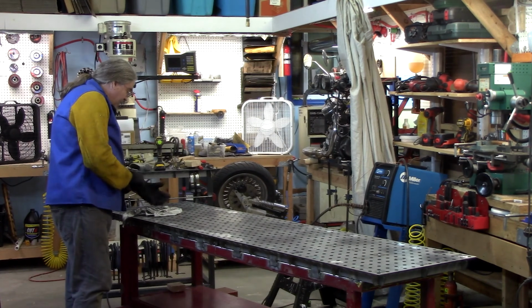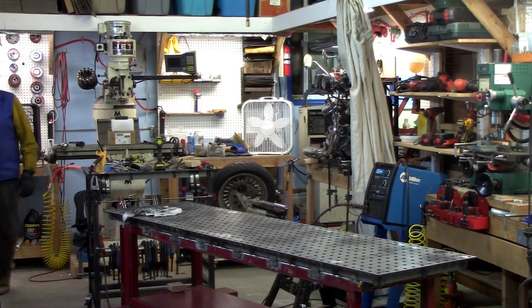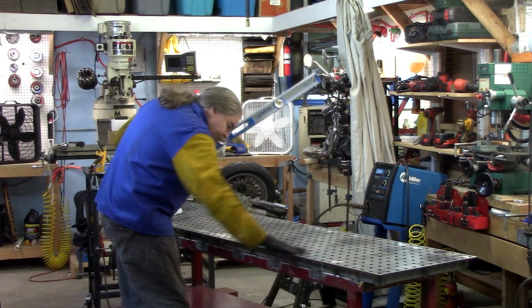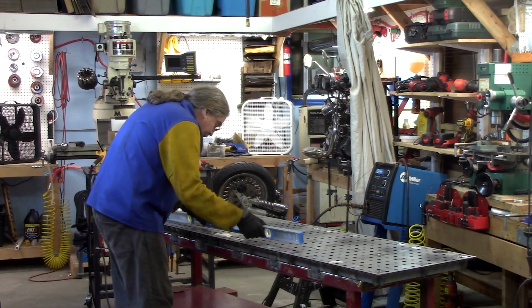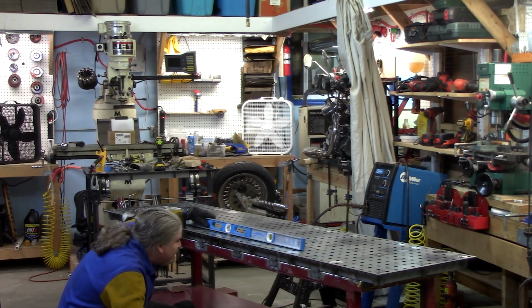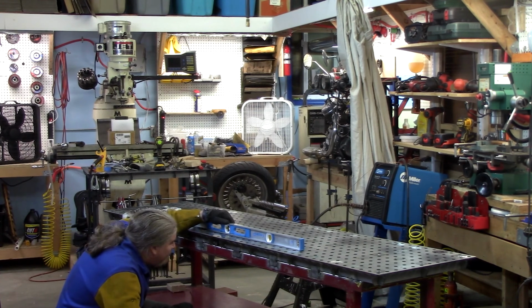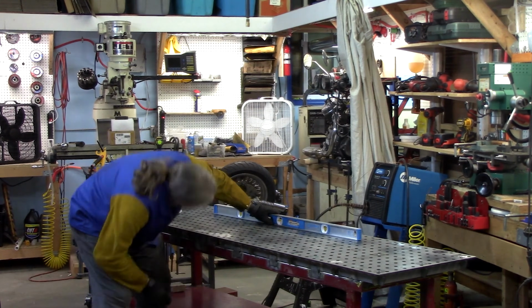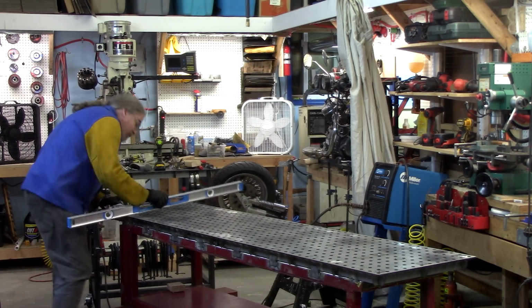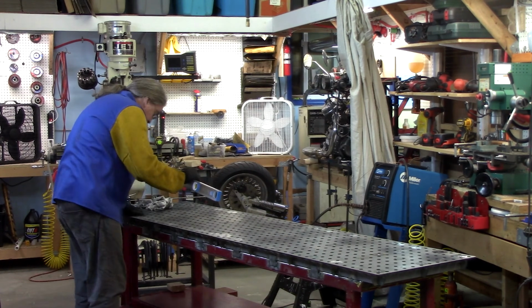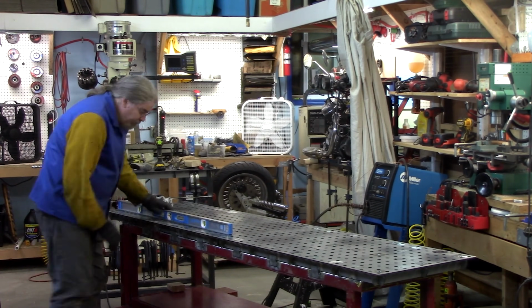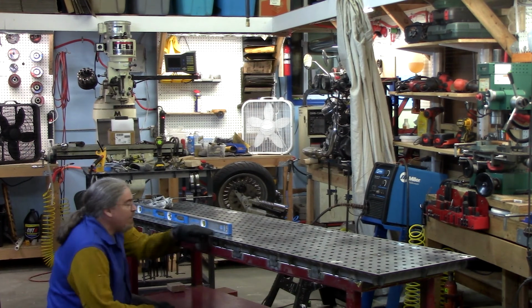I pulled out the Truth Teller straight edge and checked it across the table and was surprised at how good it came out. Nowhere on the table had more than 3 thousandths gap under the straight edge in any position I could find. I don't have an 8-foot straight edge, but this table's flatness, from everything I can tell, came out better than my 2-foot by 3-foot table. And it will be more than sufficient for a motorcycle frame jig base.